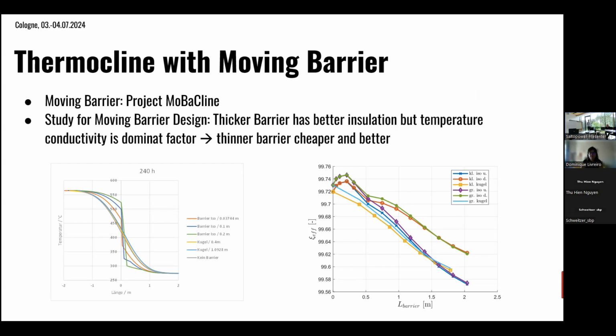If it's thin enough, then you just need to have some sort of insulation material inside, and then the steel of the barrier is adding enough weight for the barrier to sink in the hot salt, but to float atop of the cold salt. So the density of the barrier needs to be somewhere between the cold and the hot salt density. Otherwise, if it's too light, it will float atop. And if it's too heavy, it will sink down. If you had a very thick barrier of, say, 1 meter in thickness, and you fill that up with insulation material, which is typically very lightweight, it would float. So you would have to add a lot of bricks in there to make it sink down.